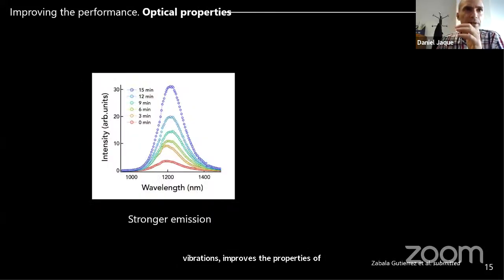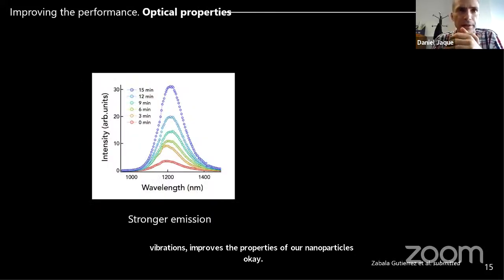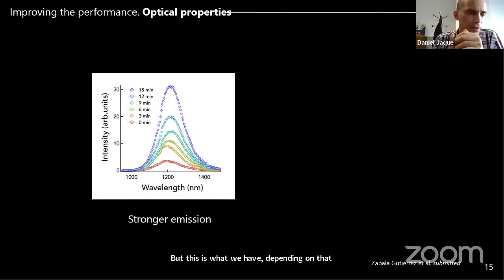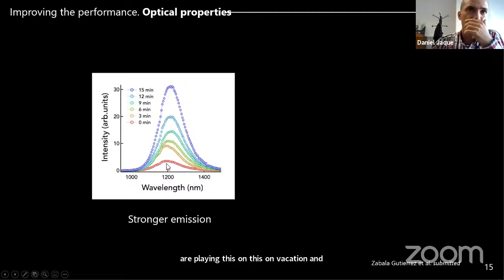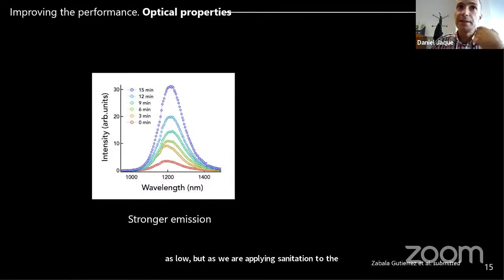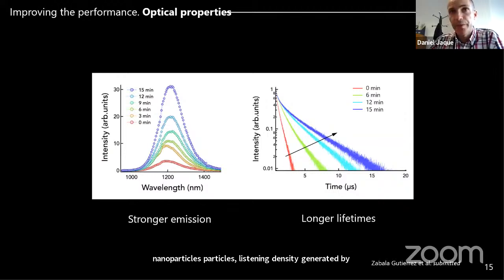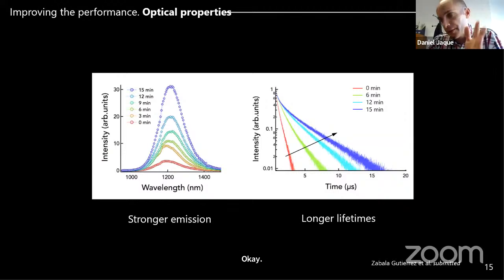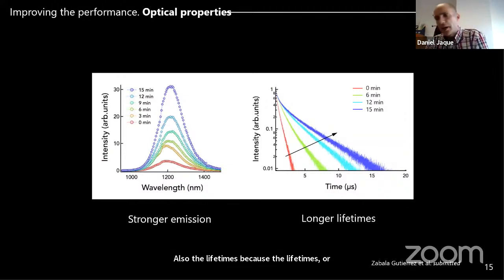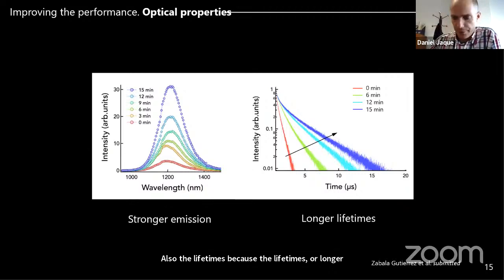Okay, so this is what we have depending on the time that we are applying the sonication. Before sonication, the emitted intensity was low, but as we are applying sonication to the nanoparticles, the intensity generated by those nanoparticles is increasing a lot, okay? Also the lifetimes, because the lifetimes are longer as you reduce the number of defects, okay?